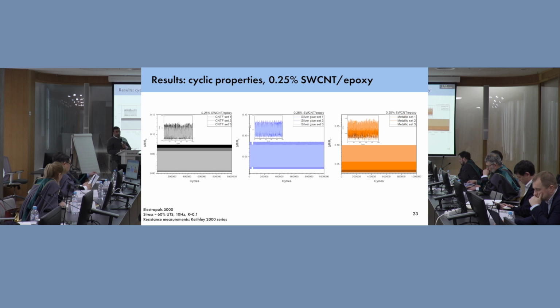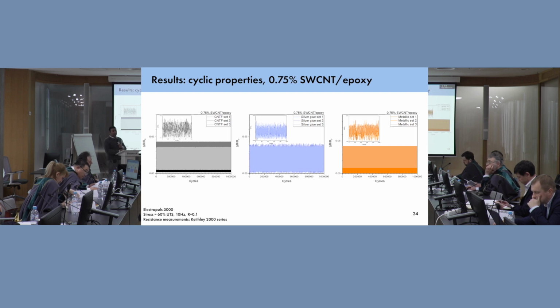They were too stiff. So in this case, we need to understand that for the single wall carbon nanotube composites, because they showed a very, very low UTS, the force of testing here was pretty low as well. So that is one of the reasons why they sustain so many cycles. We see the same behavior for a higher weight percentage. However, we start to see a little gap appear between our reading times. This again is a limitation of the machine. We do not believe that it's very good at these low stress levels for testing, but we pick up the response. So that's what we wanted to see.